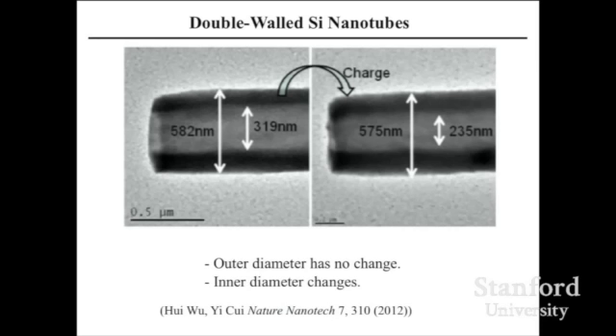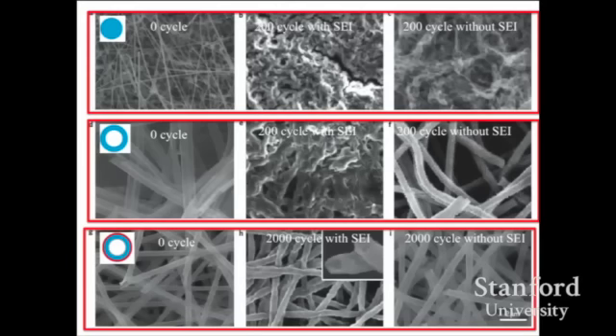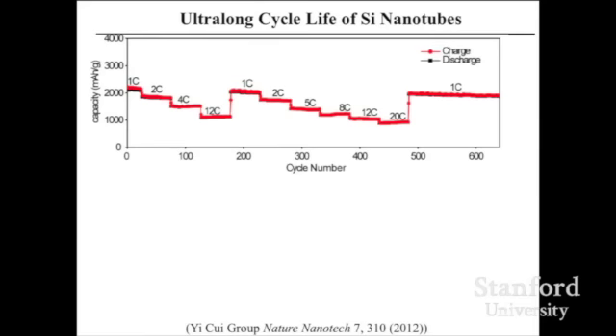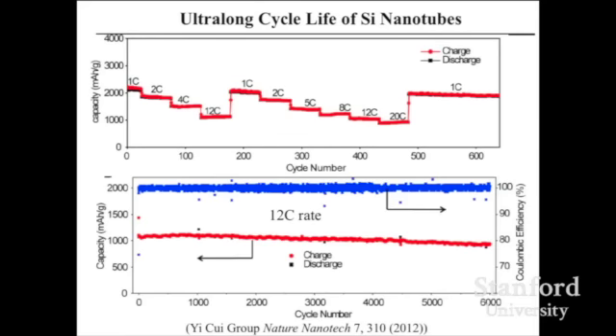This is really beautiful. You look at this, you put lithium in, and the outer diameter is almost the same, but the inner diameter now shrinks, really confirming that expansion can go towards the inside. Comparing silicon wires, single wall hollow tubes and double wall hollow tubes after 2,000 cycles, you look at the surface, it's beautiful and clean. It doesn't decompose much electrolyte, but the other two cases decompose too much. So this confirmed the double wall tube is stable. This allows us to run 6,000 cycles in the half cell, at least proving the material is now stable.